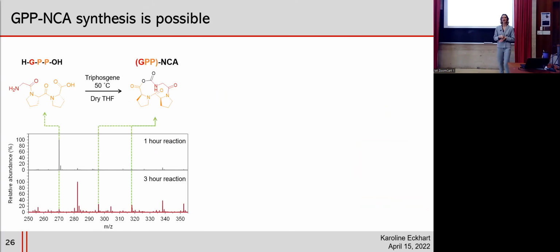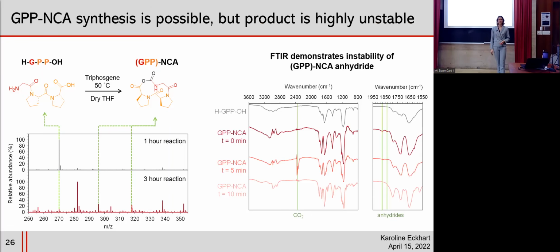But with the amino acid oligomer in hand, we cyclized it to form this GPP-NCA macrocycle, which we were able to confirm the successful synthesis of using high resolution mass spec, where we saw the exact mass adducts representing the GPP-NCA. But unfortunately, this material is extremely unstable, and we can actually witness its instability in real time.